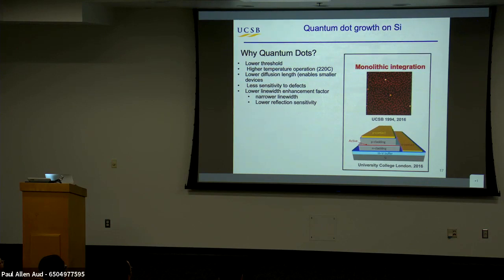And so traditionally, people like quantum dots because they're lower threshold, and indeed they are. Higher temperature operation, the highest temperature lasers are all quantum dot lasers. The lower diffusion length means you can make smaller devices less sensitive to surface recombination. So we make very small rings and get thresholds below milliamp as a result. And in particular, we got started in this because of the less sensitivity to defects. We can put literally thousands of dots in the area of one dislocation. And so you get some effect to the dislocation, but not so bad. You'll see more about that.